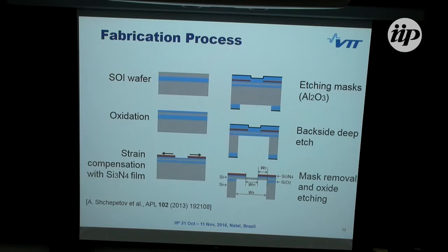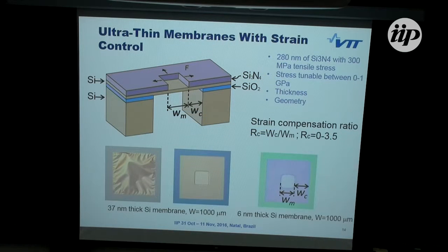And it goes like this. SOI wafer oxidation, then we put a silicon nitride film on top, and this now has tensile stress, and we can control the amount of stress there. And then we do the etching from the backside, removal of the layers, and now we have a structure which looks like this. We have the strain controlling layer here, and it pulls the membrane flat like a drumhead membrane or diaphragm. This is convenient because one can first control the stress between about 0 to 1 gigapascal, so that's one handle one can change or control the strain.